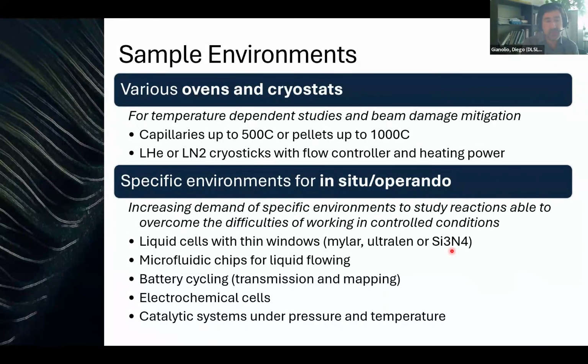cells where you can perform electrochemical experiments, again with liquid flowing, or battery cycling. And this would also need electrical connections that are going into the chamber so that the potential can be applied to cycle the battery. And some of them allow not only just transmission or fluorescence measurement, but also mapping, with a bigger window. And then there are a few catalytic reactors that allow to study the system under pressure or temperature.